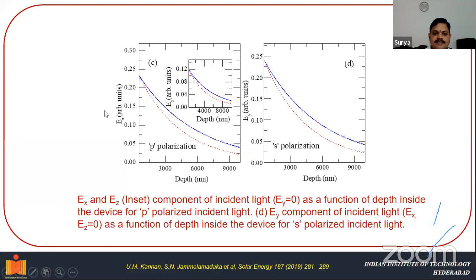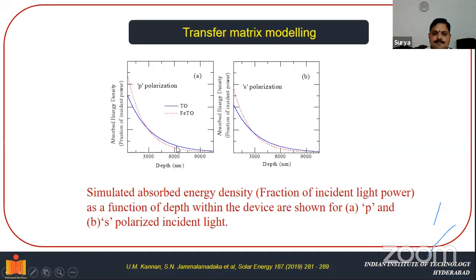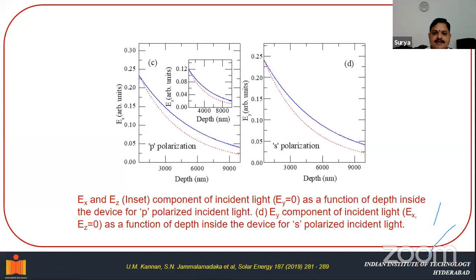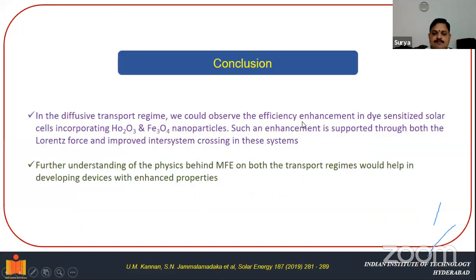So we also tried to calculate the Ex and Ey components with the depth. What we could see is that for iron added devices, the Ex and Ez components of incident light as a function of depth inside the device for P polarized light, and the Ey component for S polarized light, actually decrease. More light is absorbed by the device for both the S polarization and the P polarization.